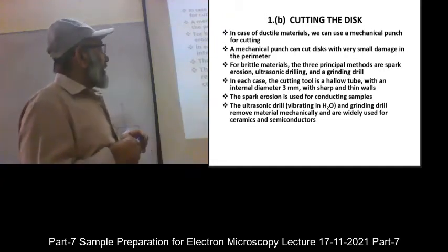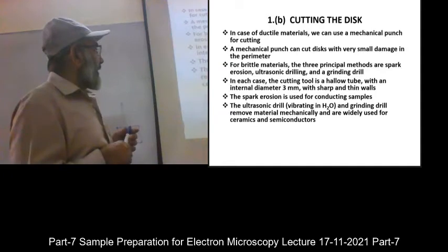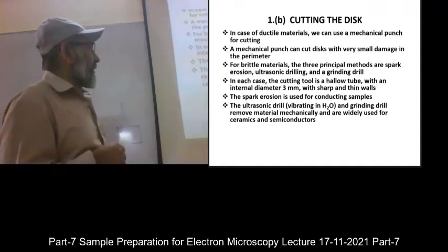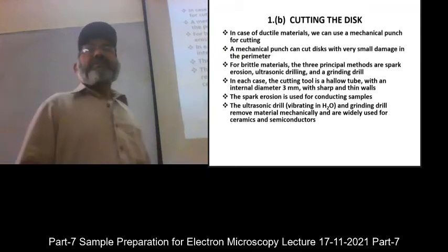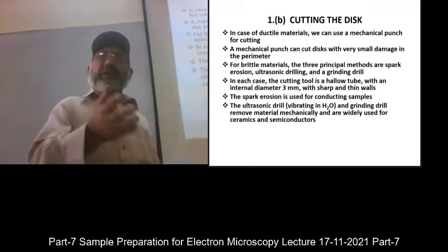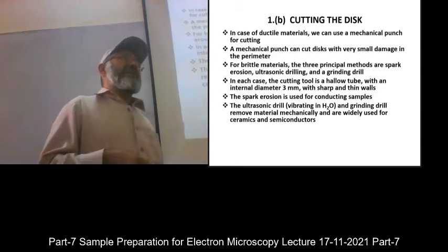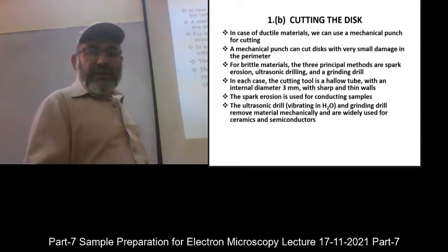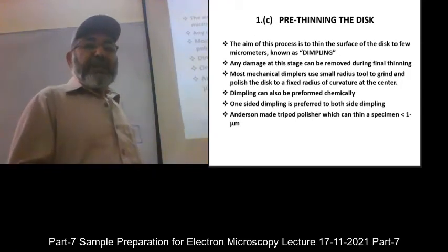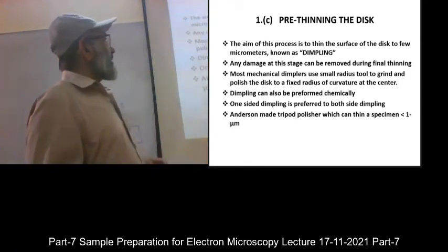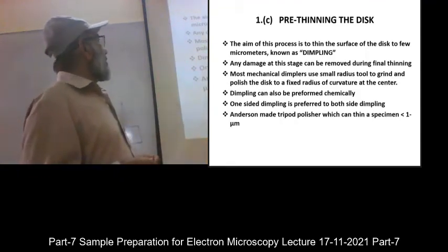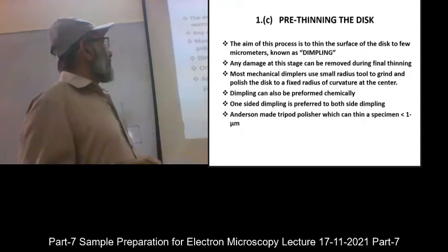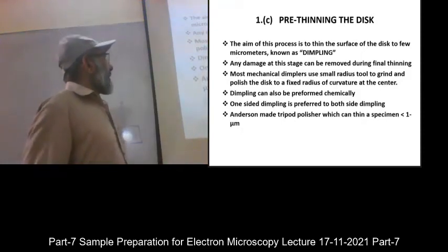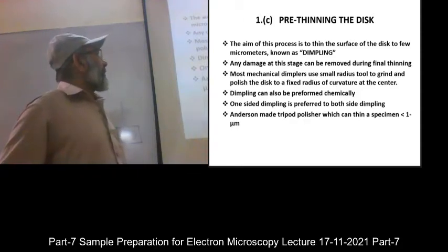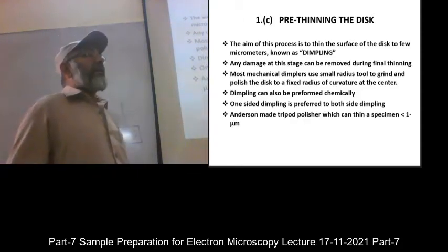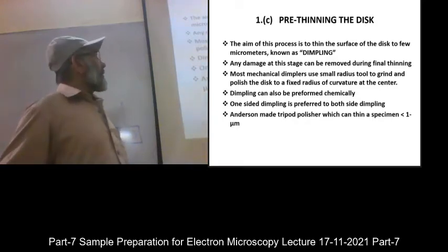The spark erosion is used for conducting material. An ultrasonic drill, vibrating in H2O, and grinding drill remove material mechanically, and are widely used for ceramics and semiconductors, which are also not totally metals, right? So the ductility is not usually there. That is why they are supposed to be treated like brittle material. Pre-thinning: the aim of this process is to thin the surface of the disc to a few micrometers, known as dimpling, as I explained it. Any damage at this stage can be removed during final thinning. Final thinning is that of argon ion thinning, right?